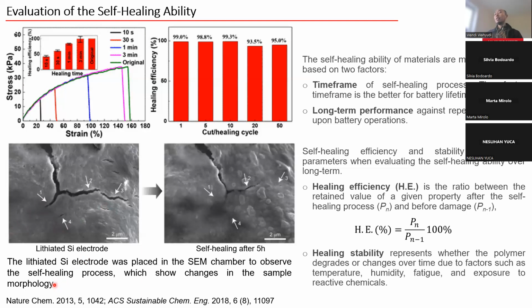Taking an example from this Nature Chemistry paper, the authors show lithiated silicon electrodes, and they observe how these lithiated silicon electrodes recover their initial structure by exposing them in the SEM chamber. They could observe that the self-healing process can take place, but is not fully complete even after 5 hours. And instead, the surface of the sample changed, maybe because of the bombardment of the electron beam in the